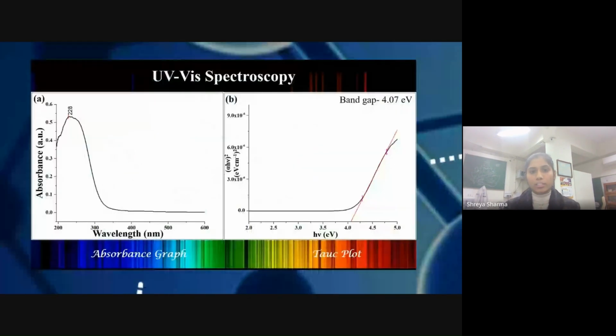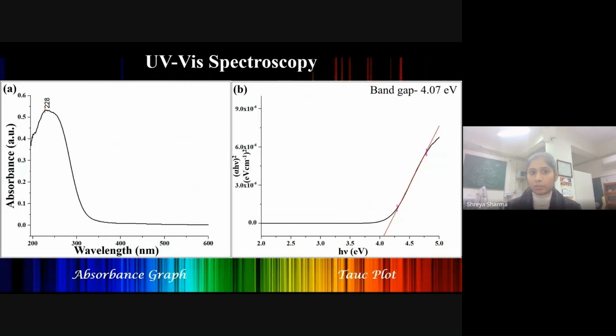Then the optical properties of the material were studied using UV spectroscopy. Here we can see the absorbance graph of the material. It shows that the material absorbs mainly in the UV region, with the maximum absorbance peak at 228 nanometers. And using this data, a Tauc plot was obtained, using which we found that the band gap of the material was reduced to 4.07 electron volts.